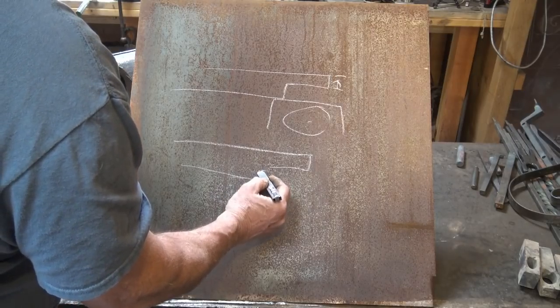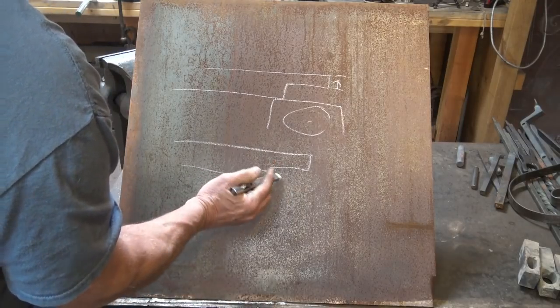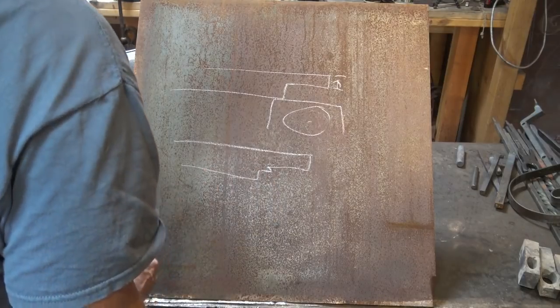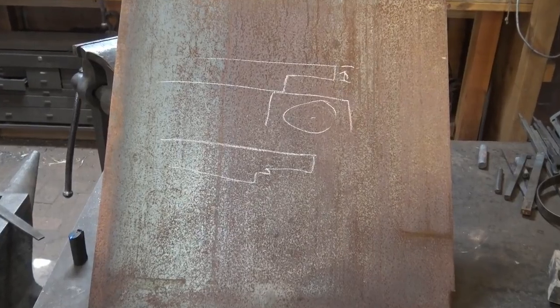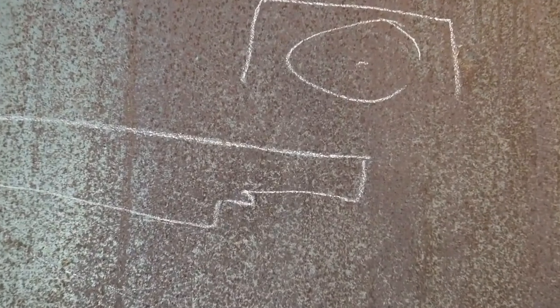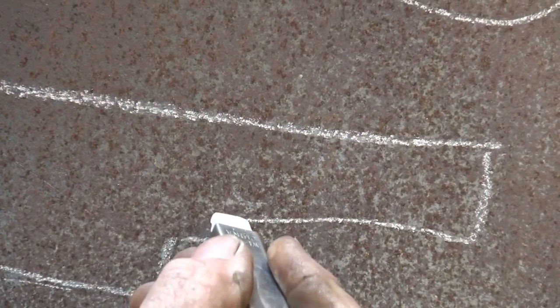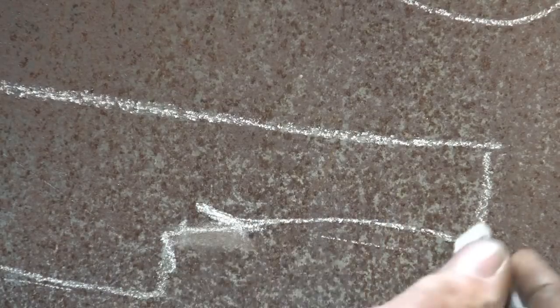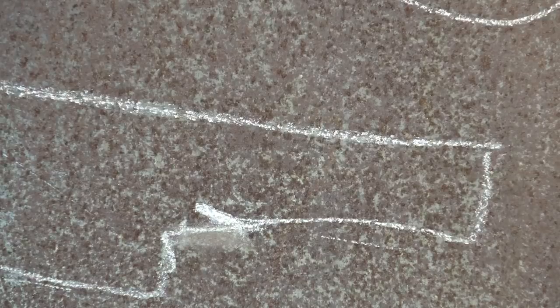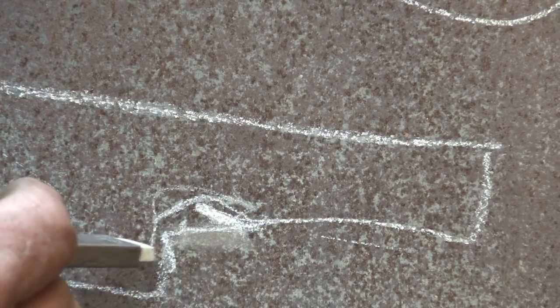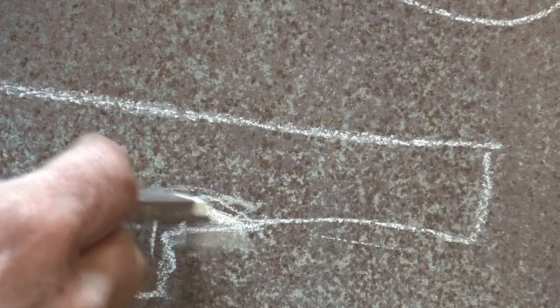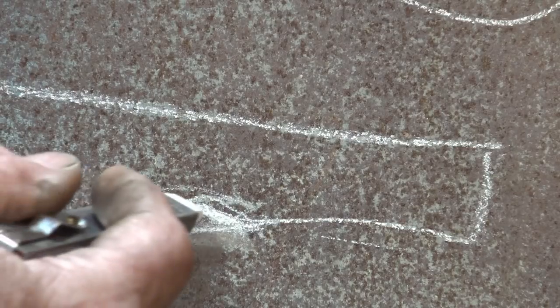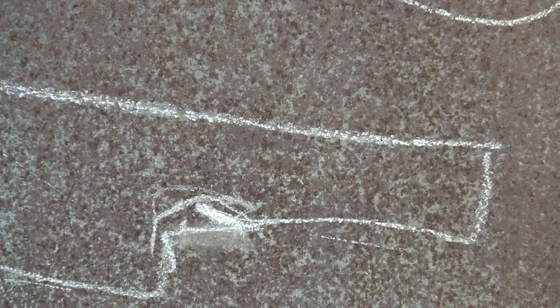You're going to start forging this up, but there's going to be material here that is pushed this way, and you're going to end up with something that looks like that. And as you forge that down, that becomes a cold shut. So this just ends up with a little crack there. You end up with this, but this is forged in here, and this is going to look okay, but you've got this little thing in here you forge down. That is a stress point. That's where that's going to crack and break. It's better off actually filed out and left around, even though that's ugly, then leaving that little seam in there because that does want to break easily.